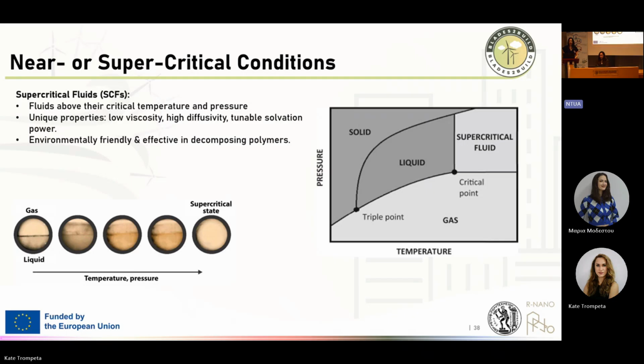And these are more environmentally friendly solvents, because usually we use water, acetone or alcohols. The supercritical point of water is around 375 degrees and 220 bars, which is actually really high. However, acetone is at 235 degrees and almost 50 bars. So acetone reaches the critical point quicker than water.